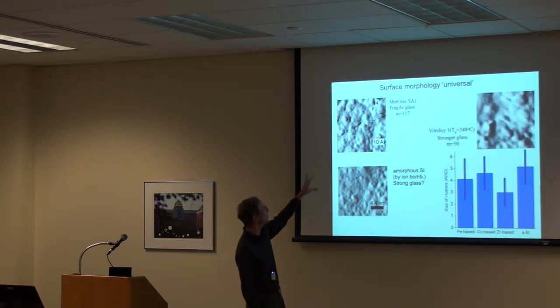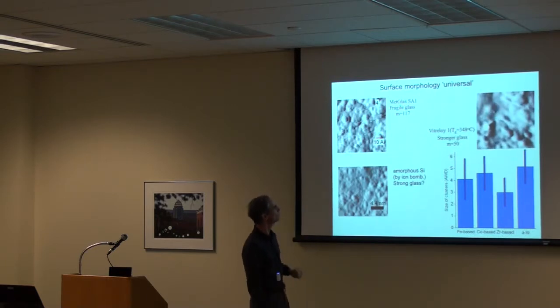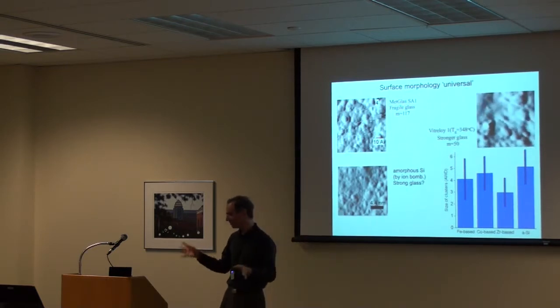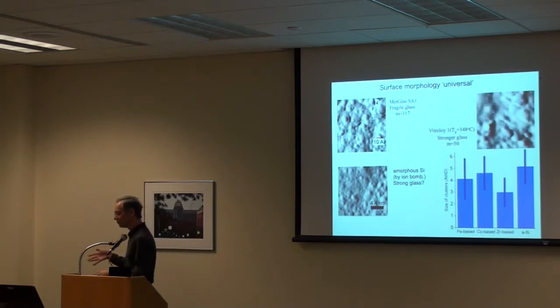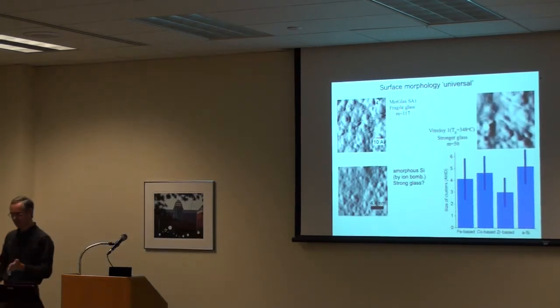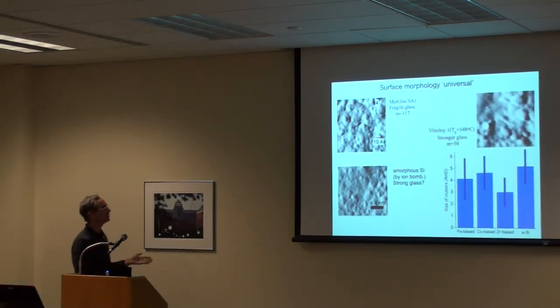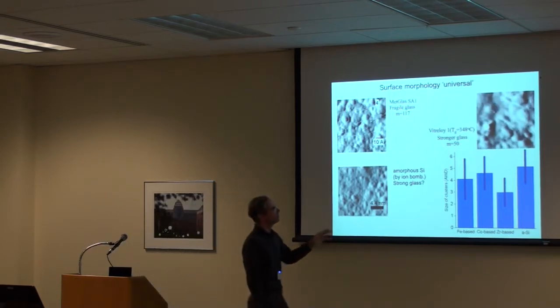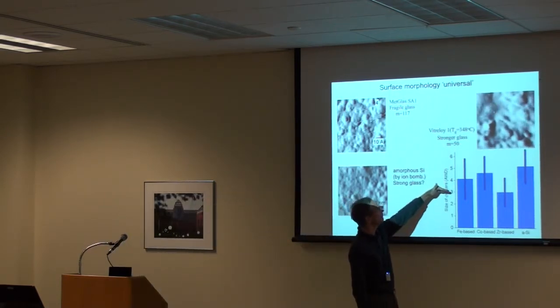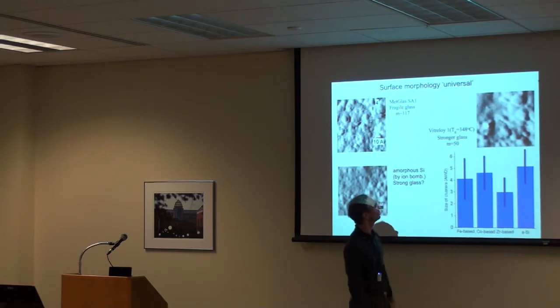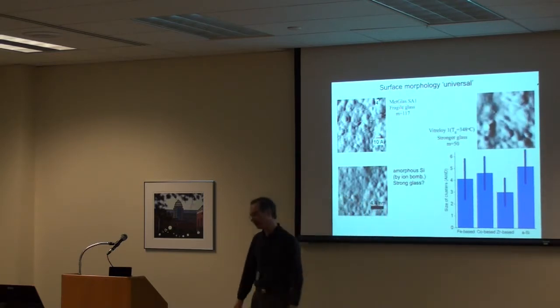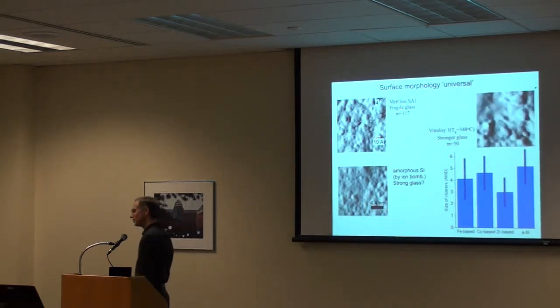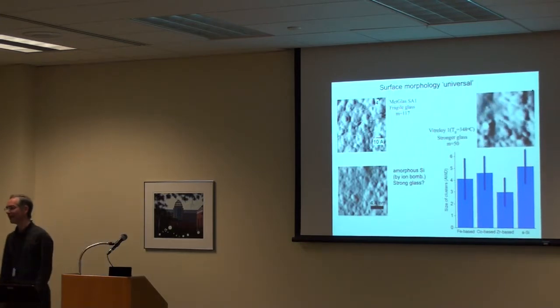Where you look at it on metal glass surfaces or silicon surfaces that are done by different kinds of methods. We can do them by ion bombardment, as I said, we could do them by vapor deposition from the vapor phase. You find that you get cluster size distributions that within uncertainty are about 3 or 4 atoms in diameter. Not very far away from what's predicted by this theory that says there should be 5 atoms in diameter.